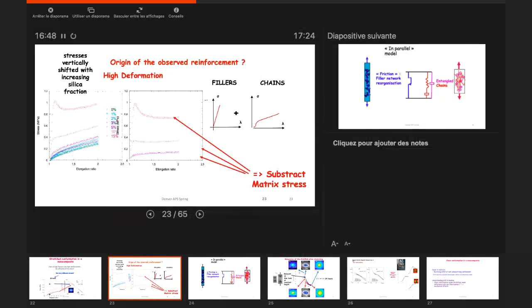If you take this perspective, then for things like the Mullins effect, the idea is that it's particle networking that dominates the physics, right? Yes, that's been proposed. I think you're coming back and reinforcing that viewpoint. Both the Payne effect and the Mullins effect are coming from particles. I think you can make that big statement. That's the bigger message from your whole thing.